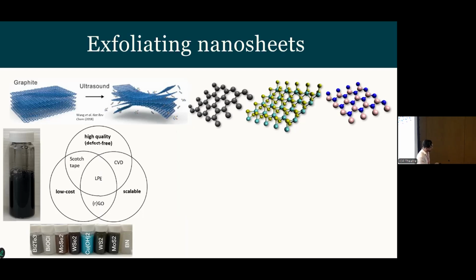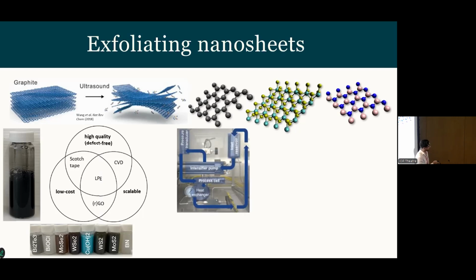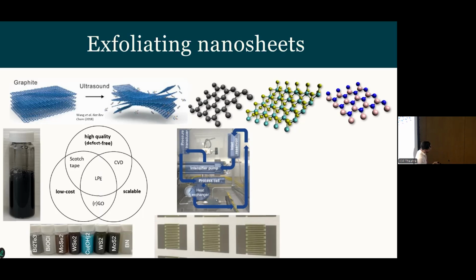And these have various interesting functionalities, lots of high K materials, lots of electrochemically active materials, some thermoelectrics, which I'll mention again later. And we're now producing these at pilot scale, in a liters to kilo scale process that uses high pressure homogenization to produce these nanosheets in large quantities. The main advantage for us there is it's allowing us to make measurements that are not possible when we're working at microgram scale. That allows us then to do things like print these, and this is printed with a domestic inkjet printer, graphene electrodes and molybdenum disulfide in the channel. So it just gives you an idea of the simplicity of the processing and the versatility that we hope to have.